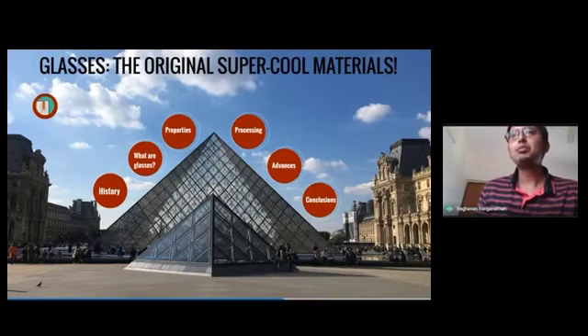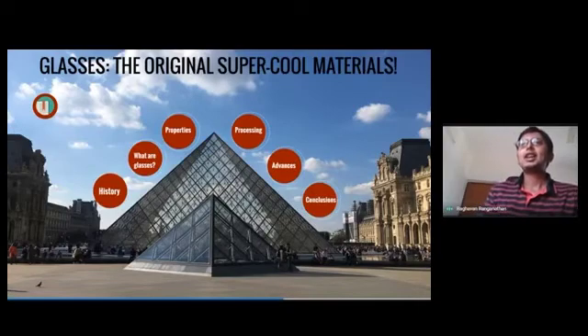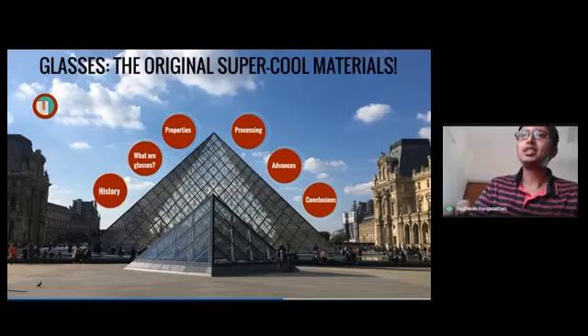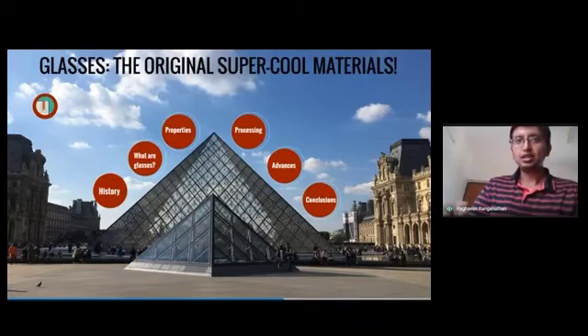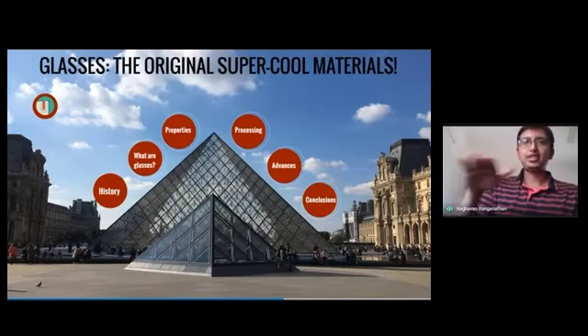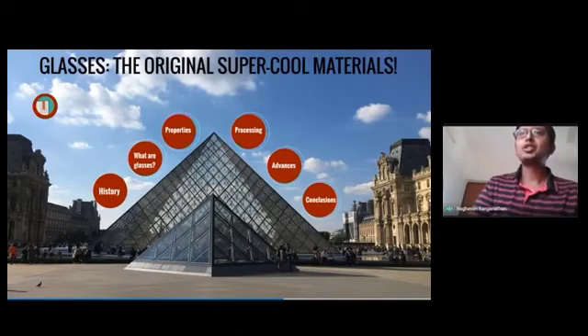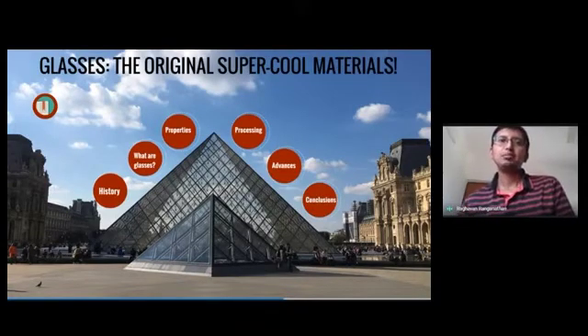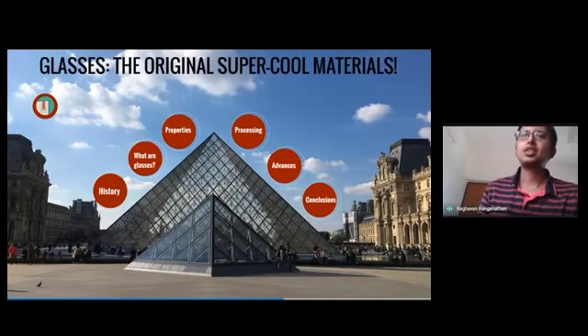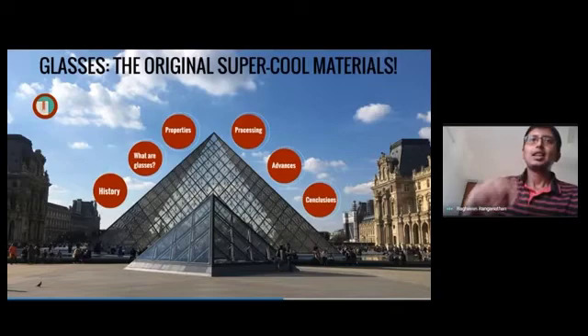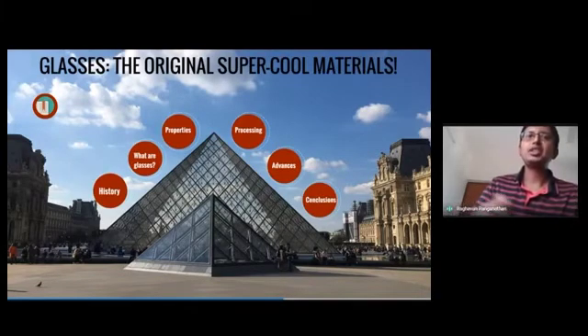What was also technologically very important is what's called the float glass process. Essentially, we take the raw materials, heat them up in a furnace, and then pass them through molten tin. This molten tin is very crucial because it forms a very nice layer over which the glass can be rolled into flat sheets. This allowed the process to generate a very large volume of sheet glass that was used in construction. Now, modern glass forming began with these processes, but there was a lot of research and technological innovation that went into forming these glasses. Processing these glasses is one of the important ways of enhancing the functionality of the glass.